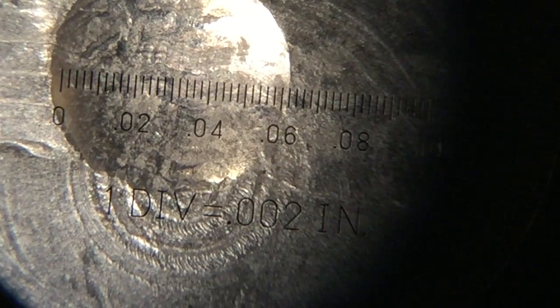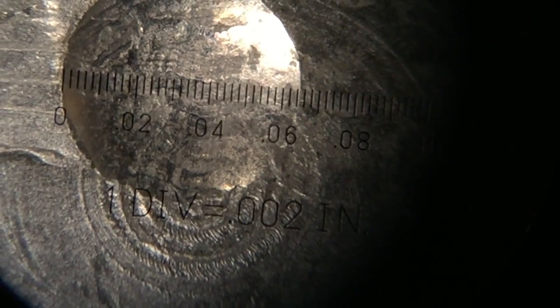When we look that up, we determine what the Brinell hardness is — in this case 12.5. A reading of 0.064 is 12.5, and we've had them ranging all over the place. Let's see if I can move over just a little bit and get that edge better — there we go. That's much better. Now we're a little bit off on the left, so let's work on that.